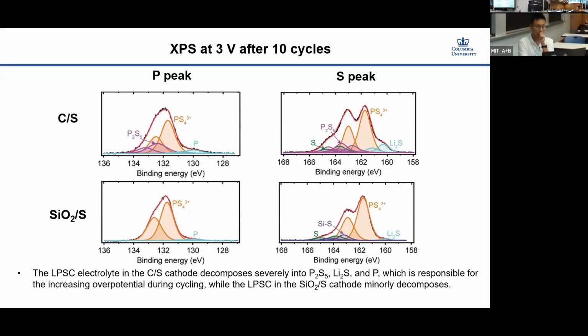And the little decomposition of the electrolyte in the silica matrix is also confirmed by XPS studies. In both the phosphorus and sulfur peaks with the silica matrix, you don't see the phosphorus sulfide peaks seen in the carbon sulfur composite. And the existence of phosphorus sulfide indicates the decomposition of the electrolyte. So we can confirm that there is actually little decomposition of the electrolyte.